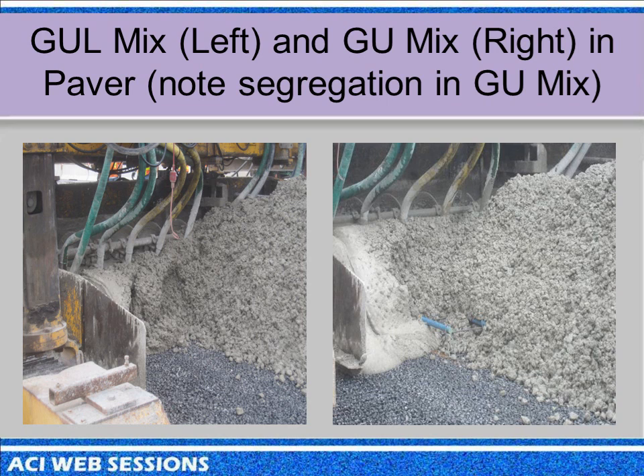Interesting thing though, in the paving machine itself, this is the Portland limestone cement mix, so it's being augured out to the edge of the slab, and there's very little segregation of the mix. With the normal mix they were using, they were getting some segregation of the fines near the edges of the slab. And you see the dowel basket. So actually the mix was an improved mix in terms of preventing segregation with the limestone. And that's something we've noticed on all the jobs. Typically the finishing is easier with the limestone cements because of the increased particle fineness.